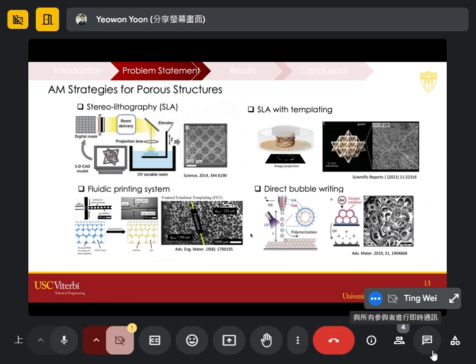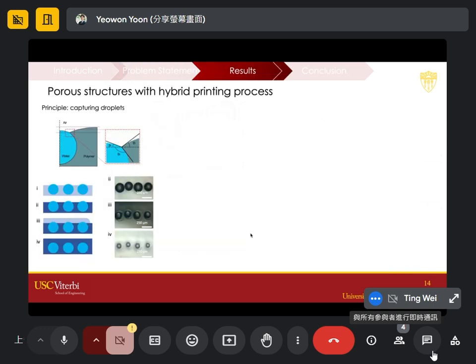They have a coaxial nozzle, and they can print either closed cells or open cells with size control in the 3D bulk system. So there still remains the challenge of controlling individual pore sizes and distribution, and also controlling each cell's connectivity in that manner. So in our lab, we tried to find out the way to incorporate porous structure with 3D printing. We came up with this idea using a relatively simple experiment.